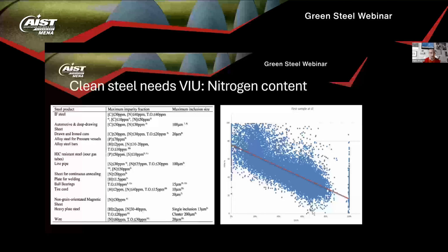You see that I would say that whereas scrap can bring in up to 100 ppm nitrogen coming from many sources in scrap, DRI is likely to bring in 20 to 25 ppm dissolved nitrogen, which is also a factor that points to the fact that high quality steel cannot do without a virgin iron unit, which is why the steelmaker would like to integrate upstream.